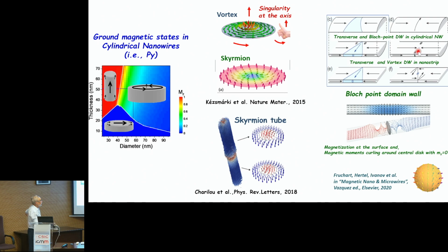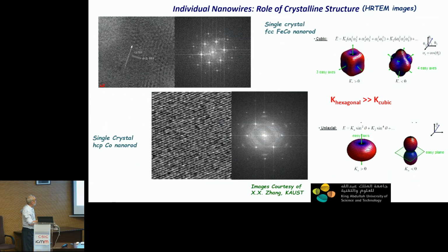This is very, how to say, unstable, it's metastable. So this requires a lot of energy, and as soon as it is formed, it tries to move to one end of the nanowire to be annihilated, because it creates a lot of energy. Well, this is an image, some micromagnetic simulation of a Bloch point at the surface and inside. So here we have zero axial magnetization. We can talk later if you are interested. But from now on, I'm going to talk only about the latest results on individual nanowires.